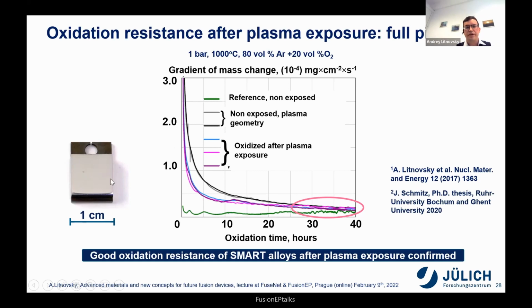Look at the shape of the plasma material sample. It has a hole, it has this loop. You see these black parts, which we cannot clean. So these exact parts, and you can see this geometry without any plasma exposure, have the same trend of mass change. And the plasma exposed samples, which are here reddish, are performing even better. The smaller difference, the better. But the important message: after 30 hours of operation, this geometry effect vanishes and only the material plays a role.